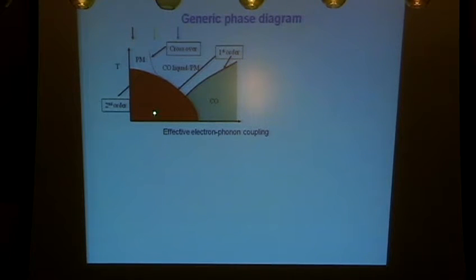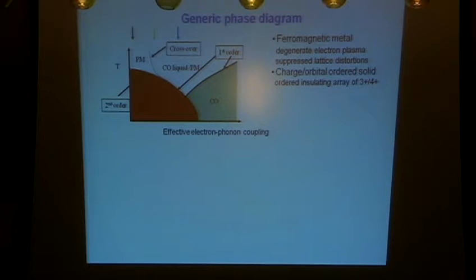Temperature is up on this axis, and generically I put in some kind of electron-phonon coupling along this axis, where if the electron-phonon coupling is weak, I have only magnetic interactions, and I get a transition from a paramagnetic metal to a ferromagnetic metal in the usual way. Whereas if the coupling to the lattice gets big, eventually I get these charge-ordered phases which exist out here. And the real physics of manganites, of the so-called colossal magnetoresistance, is in fact associated not with this phase or this phase, but actually the phase which exists up here.